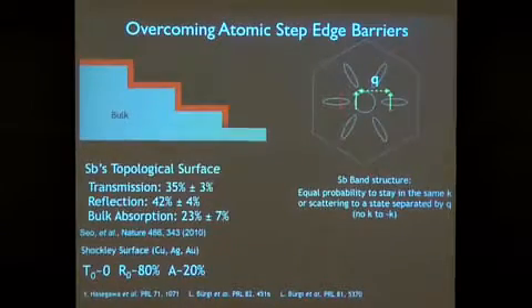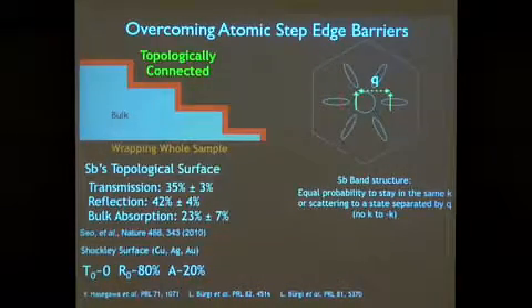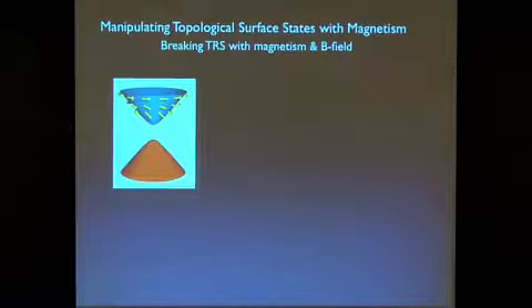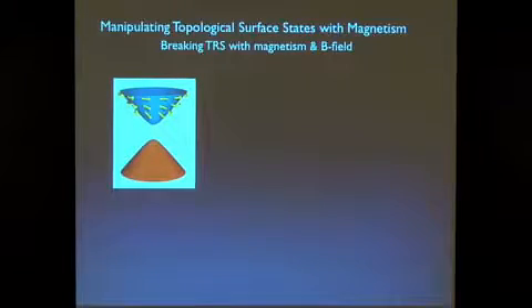So what this experiment showed us is that unlike ordinary surface state, topological surface states are connected between the different terraces of the material. So if you put an electron in one terrace, there is a likelihood that it will leak out and go to the next terrace, which is something we've never observed with other surface states. OK. So what's next? So that was perfect.